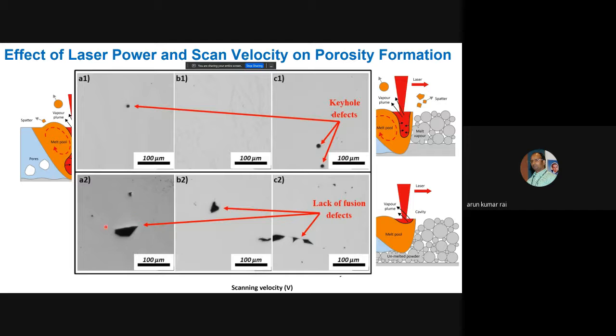If you have some uneven shapes, those kind of porosities are seen, they are basically due to non-melting. So you have either used less power or you have used very high scan speed, that can lead to this kind of defect formation in the material. Okay, so just by looking at the microstructure one can recognize. And this we have to minimize.